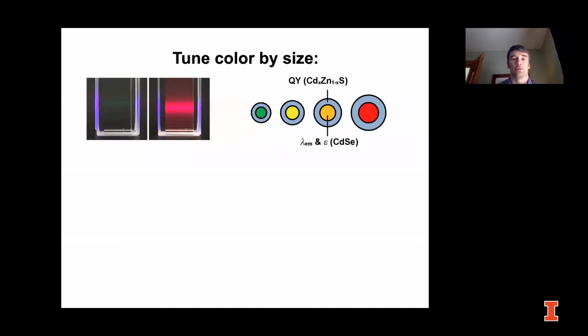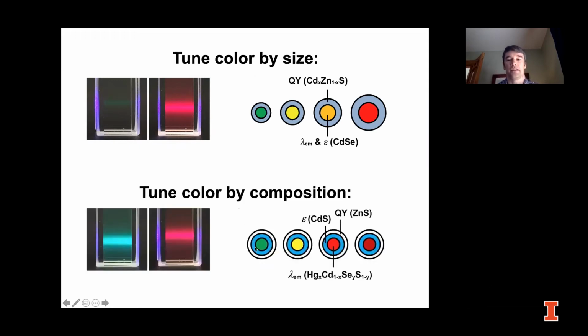So to do this, we redesigned these nanocrystals. Actually, this was done originally by Sung-Jun Lim in our lab about 5 years ago, which is to take these materials, which I inferred previously have been problematic because of how different they are in brightness. So we re-engineered these to have a very similar brightness by replacing the materials. We now make them out of what is shown in the bottom here. These are quaternary alloy materials called mercury cadmium selenide sulfide. We use these to replace the prototypical materials shown in the top, called cadmium selenide. And in doing so, we can change the color without changing the size.